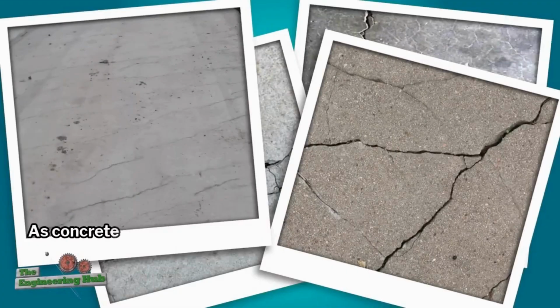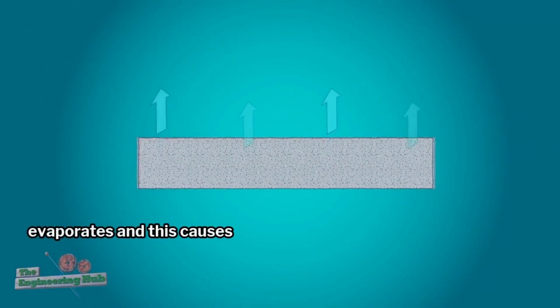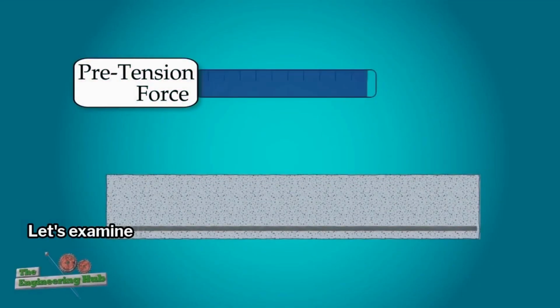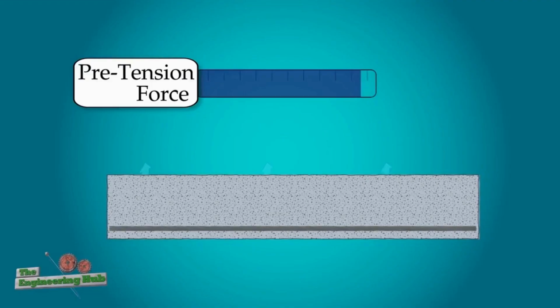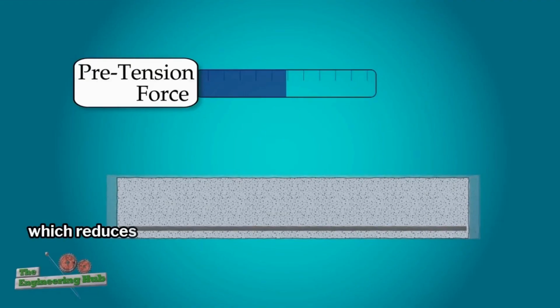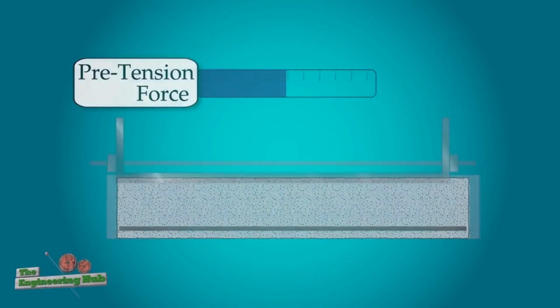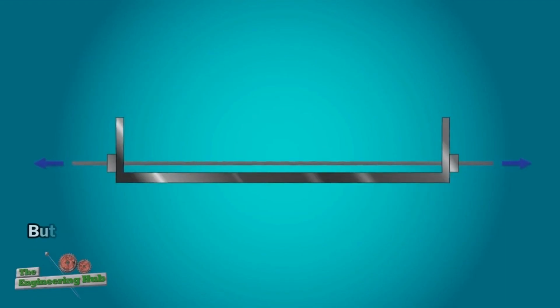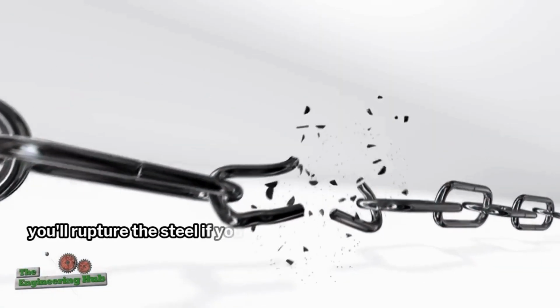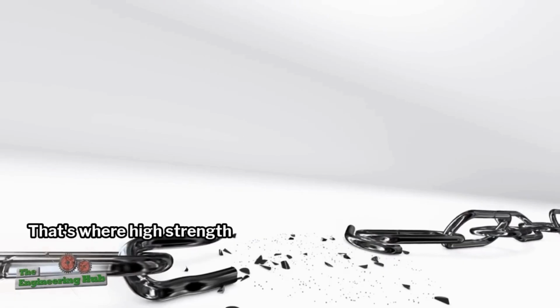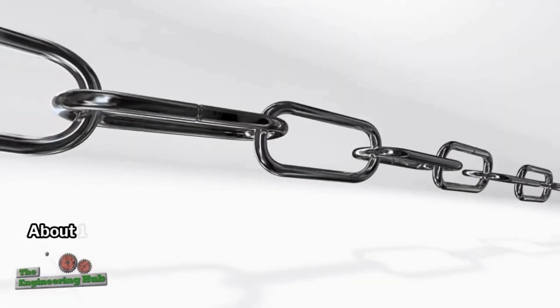Early pre-stressed concrete designs made the mistake of not properly accounting for concrete shrinkage. As concrete cures, the water inside it evaporates, and this causes shrinkage, which can occur for up to 18 months of curing. Let's examine how this shrinkage would impact our pre-stressed beam. As the concrete shrinks, so too would the pre-stressed steel bonded to it, which reduces the tension force in the steel, and thus reduces the pre-stressing load. So, in order to offset the losses of shrinkage, you need more pre-stressing. But, at a certain point, you'll rupture the steel if you pre-stress too much. That's where high-strength steel reinforcing comes into play.